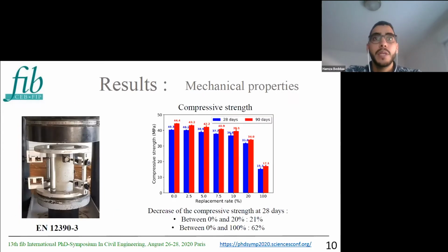For mechanical properties, we start with the compressive strength. The compressive strength was measured on cylindrical samples, and the test was carried out at 28 and 90 days. So for the result, the compressive strength decreases as the replacement rate increases. This decrease is significant, and it is about 21% for a substitution rate of 20% and reaches 62% for a total substitution.